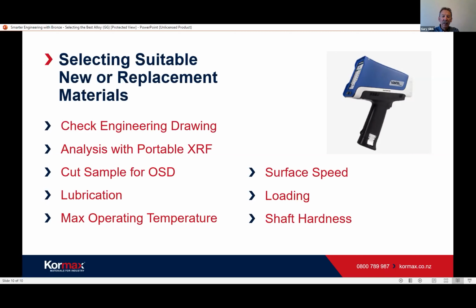The loading of the whole shaft and everything is important. That's what we talked about, the strength of the materials. That's where your tensile strength and the yield strength come into it. So that's important to work out. And the shaft hardness is important. So as I said, up to around about 150 Brinell for the bush, you're okay with a mild steel shaft. After that, you've got to move to a hardened steel shaft, case hardened or whatever.